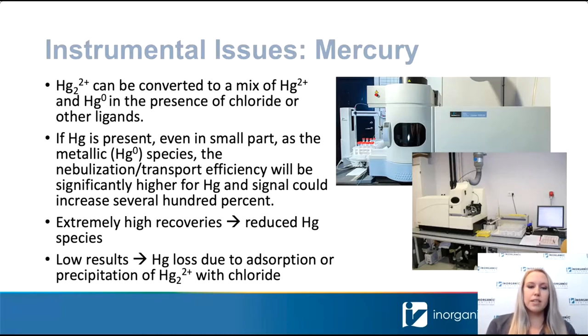Another thing that could have happened is that if your solutions are older, if they were prepared several days ago, then you could have reduced mercury species in there that has actually been lost from the solution because it is a volatile species. So if your concentrate had the dimer present and then you added that to an HCl matrix or some other ligand matrix, the metallic mercury could have precipitated and then been lost from the solution over time.